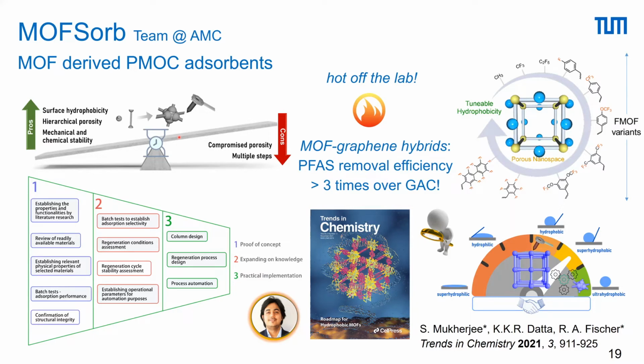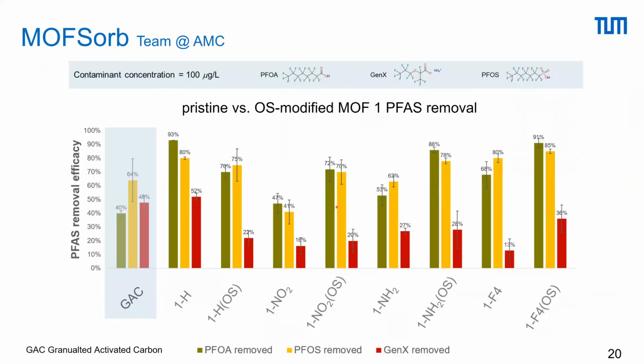You have to work against the established activated carbon, which is cheap and simple. So granulated activated carbon is the adsorbent of choice for this kind of water purification. However, there are limits, and the granulated activated carbon is less selective in the capturing of these specific pollutants. And one of the ideas is to play, as I have introduced before, with the internal surface area of these high surface area metal organic frameworks by fluorinated ligands or by other ways to play with the hydrophilicity and hydrophobicity.